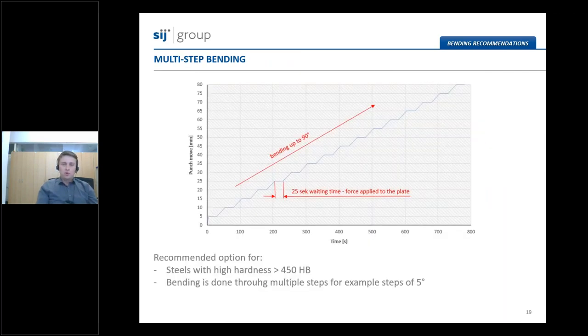We also have to point out the importance of the multi-step bending. So the multi-step bending can be a good practice when you are bending steel with really high hardness or, let's say, extremely high hardness. In this case, the movement of the punch is not continuous, but consists of more steps. So on this diagram, we have more than 15 steps to bend the plate to the final angle of 90 degrees.